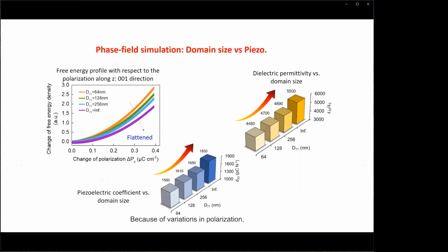Because of variations in polarization, the free energy of the system is also affected. As shown here, the free energy profile becomes flattened by increasing the domain size, leading to the enlarged dielectric permittivity and piezoelectric coefficient.